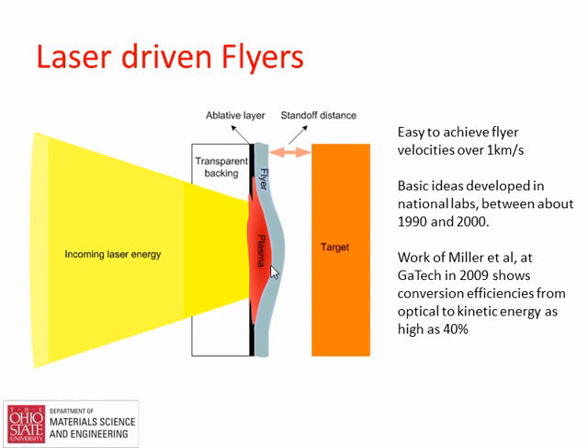Now when this pulsed laser comes in, it comes through the transparent material and basically ablates that paint because it is absorbing that energy, right? There's a very high power density, very high intensity, and that layer is ablated. It has to go somewhere, but since it is backed with some inertial restraint, the only place it can go is to push. It finds the path of least resistance, so it pushes that flyer plate at a high velocity. That flyer plate, obviously, with the laser we have, cannot be very thick or very heavy. So Huimin's been welding flyer plates of maybe 2/1000ths of an inch thickness.